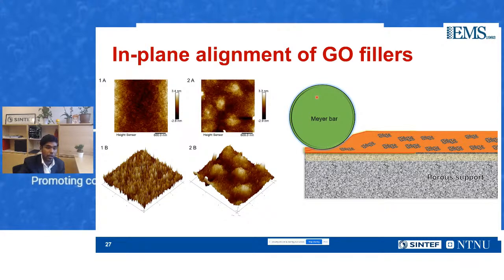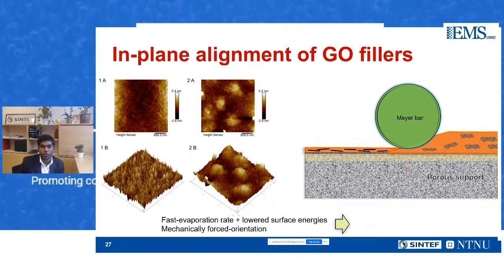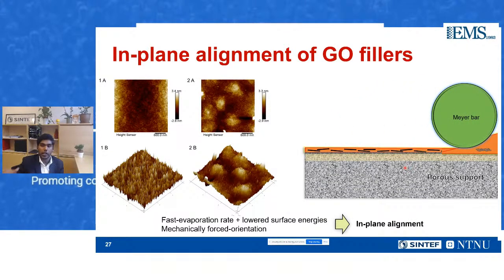For example, in a bar coating apparatus, you have a solution of graphene oxide dispersed in the polymer, and we coat it on a porous support with some pore filling agent in there. Due to the fast evaporation rate and the lowered surface energy, the 2D materials tend to align parallel to the surface of the porous support, which helps with gas permeation as we expect. That's also one of the reasons we are able to make this selective layer as thin as 200 nanometers. So this mechanical force orientation, coupled with fast evaporation and lowered surface energy, leads to what we call in-plane alignment of the graphene oxide, which is beneficial for gas permeation.